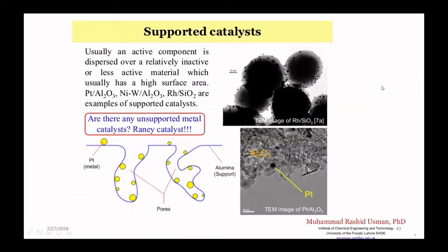Supported catalyst is mostly used in industry. Usually an active component is dispersed over a relatively inactive or less active material. It usually has high surface area. Platinum dispersed on alumina, nickel, tungsten dispersed on alumina, etc.